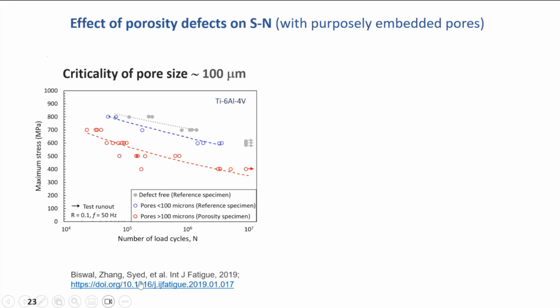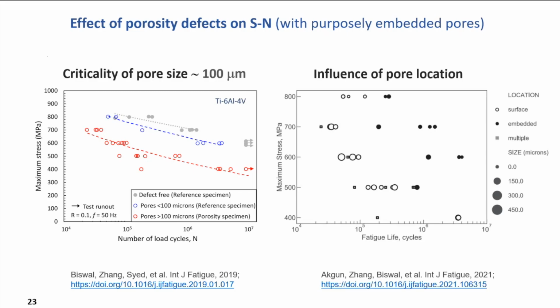So my student, Dr. Biswal, published the first paper on this, saying the critical pore size is around 100 micron. Subsequently, I reviewed a lot of papers in steel and titanium. They do agree with this number, between 80 to 110 micron, being quite a critical defect size.